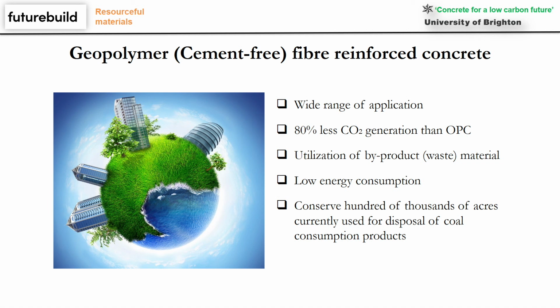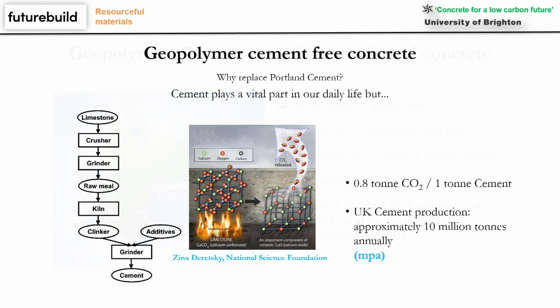So we are doing a total replacement of cement. We use only waste products, only fly ash and GGBS. And our task is not only to use waste products only, but we also want to achieve high strength and good properties so that these materials can be used for structural applications and can also be used for the repair and strengthening of existing structures. This is an application which can have a quite important environmental impact because UK cement production is something like 10 million tons annually, and we know that 1 ton of cement leads to something like 0.8 tons of CO2 emissions, so we can save something like 8 million tons of CO2 emissions annually.